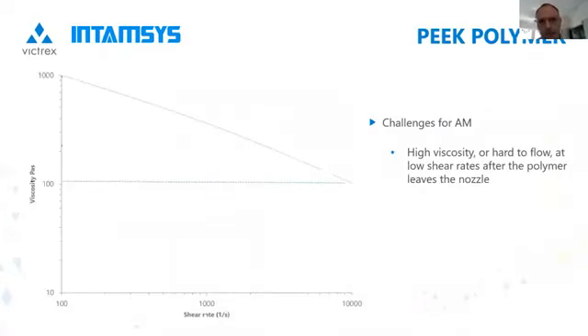Additionally, for printing using filament fusion, the high viscosity of the traditional PAEK materials can also be problematic for the machines. Here you can see a rheology graph for PEEK 380, and it shows how the viscosity goes down for PEEK, making it flow more easily when the shear rate goes up.